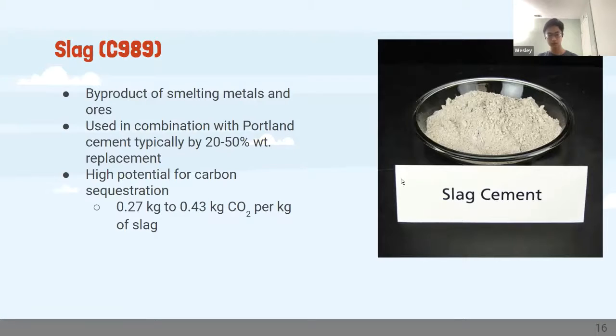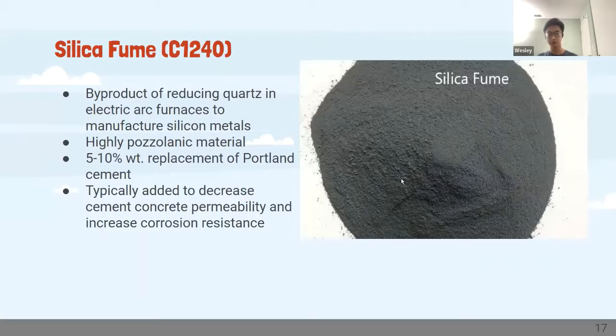Next slide. And so another type of SCM is called silica fume, and it's essentially a waste material from the semiconductor industry. Specifically, it's a byproduct of reducing quartz in electric arc furnaces, and it's a highly pozzolanic material. These typically replace Portland cement by a range of 5 to 10 weight%, and it's usually added to decrease cement concrete permeability and also increase its corrosion resistance.